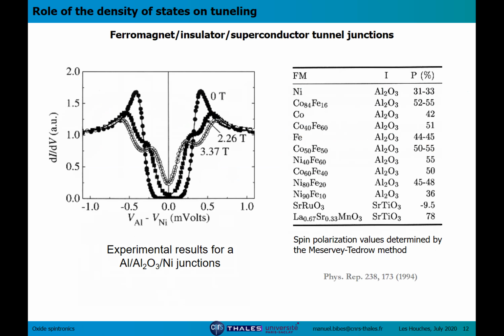So these are experimental results obtained in junctions in which the superconductor was aluminum. Aluminum can become superconducting, but at lower temperature than lead, so typically around 1 Kelvin or lower. And the barrier is, again, in most of these curves, aluminum oxide. And the ferromagnets are, as you can see, nickel, cobalt, iron, or their alloys. And you can see from the data here the result from a junction with nickel. At high field, we have clearly 4 peaks. You can look at these white dots here. You can really see these 4 peaks.